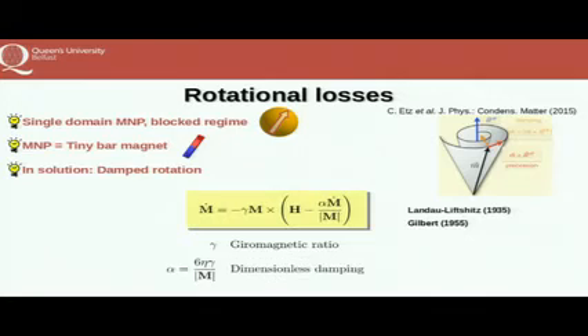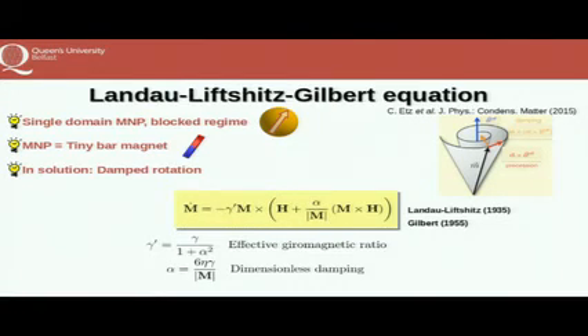So it's much better to write down this Landau-Lifshitz-Gilbert equation in an explicit form. Just to simplify the notation, I will use alpha to indicate this dimensionless damping constant. This is 0 in vacuum. And after a little bit of algebra, we can prove that the original formulation of the Landau-Lifshitz-Gilbert equation is exactly equivalent to this explicit form. You see that now in the explicit form we just have the time derivative on the left.